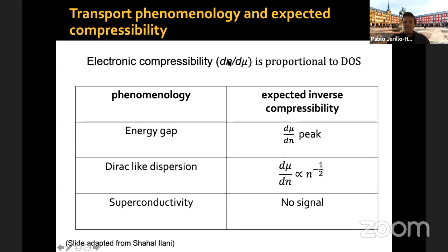This is dn/dμ. So how does the charge density in a system change as you change the chemical potential, μ, okay? Which in the single particle picture is proportional to your density of states, okay? In particular, what we measure in these experiments is inverse compressibility. So dμ/dn: how does the chemical potential change as a function of our control knob, which is the charge density. So the phenomenology, given this simple interpretation of dμ/dn as inverse density of states, is the following.